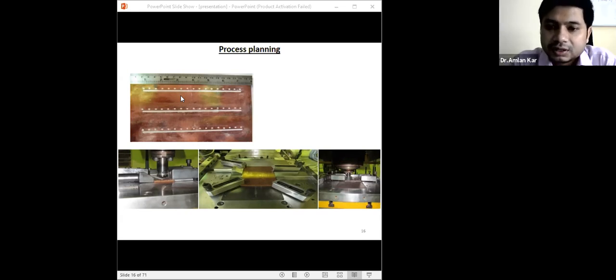So what I am telling is, after pyrolysis, the samples are processed again using the same process parameters to distribute the ceramic powder and remove the porosity, if it is available. Generally, porosity is available in the particle because when it is subjected to pyrolysis, whatever gas has evolved from the polymer creates or develops porosity inside the matrix. So to overcome this porosity effect, a third pass, or additional friction stir processing, has been conducted to eliminate the porosity.